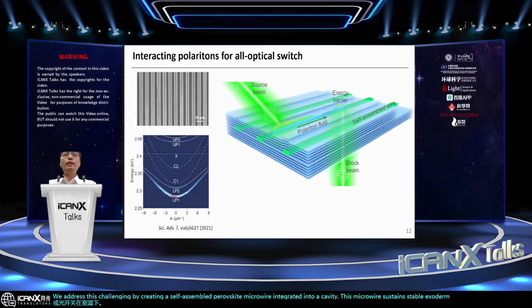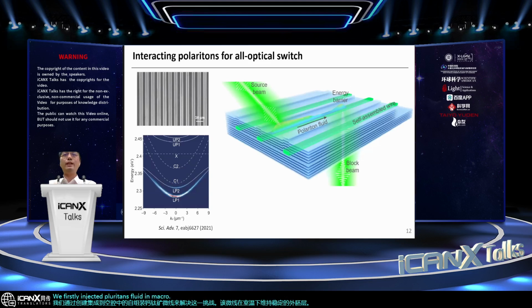We first inject a polariton fluid in the microwires via a source beam. Then, through the introduction of localized polaritons using a block beam, we establish an energy barrier leveraging the repulsive interaction between polaritons. By manipulating the time delay between the two beams, we showcase on-off control of polariton propagation.